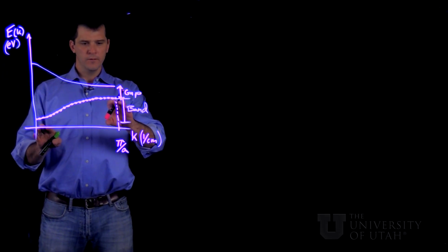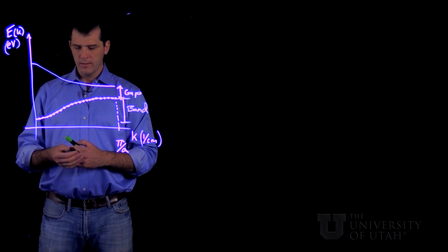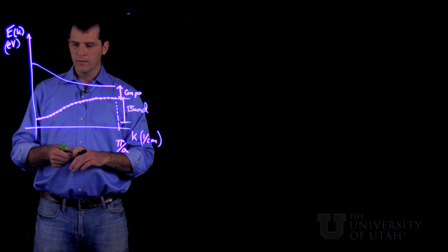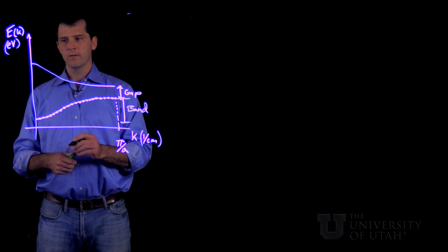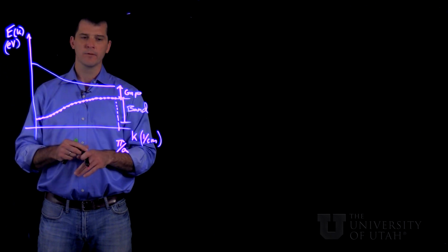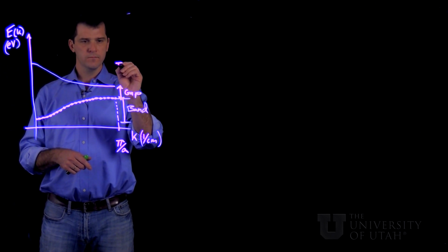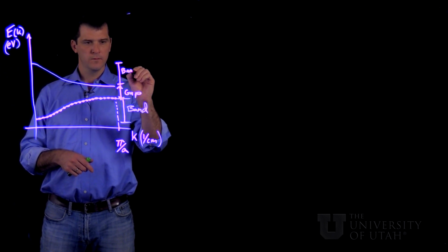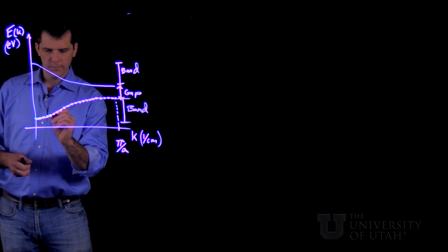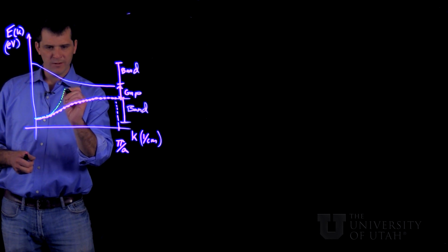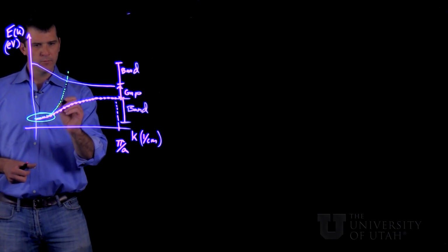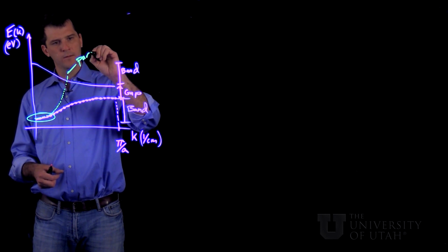So this function is a little more complicated than we want to deal with. And it turns out that usually all of the action in the semiconductor will happen right near either the top energy or the bottom energy within a band. So what we end up doing is really only worrying about the first part of this function, which is near a minimum, and we're going to approximate that by a parabola.